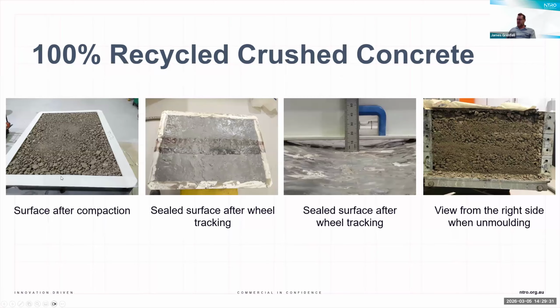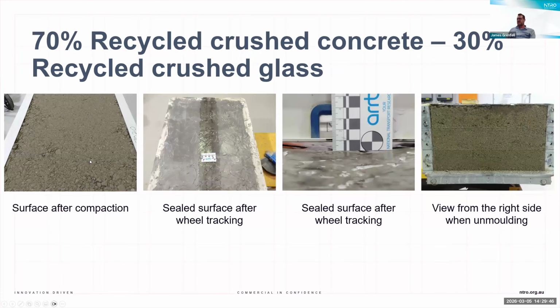So now a few images. So we tested the recycled crushed concrete, and straight away you can see how poorly graded this material is. Tested it under the wheel tracker. And this is an example of the 70% recycled crushed concrete, 30% crushed glass. Straight away, you should be able to see how much better the gradation, how much tighter the material is, which has obviously then led to improved performance under heavy loading.